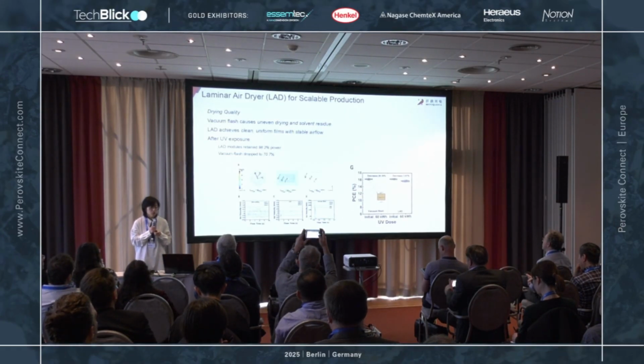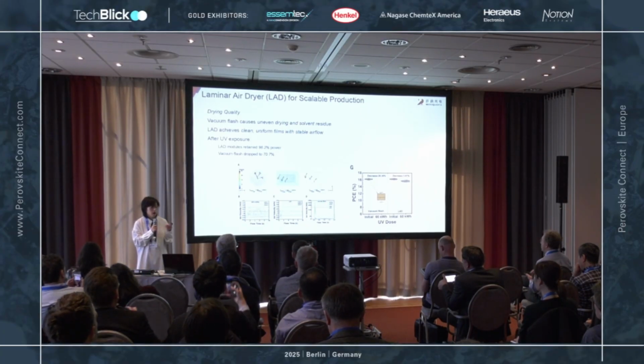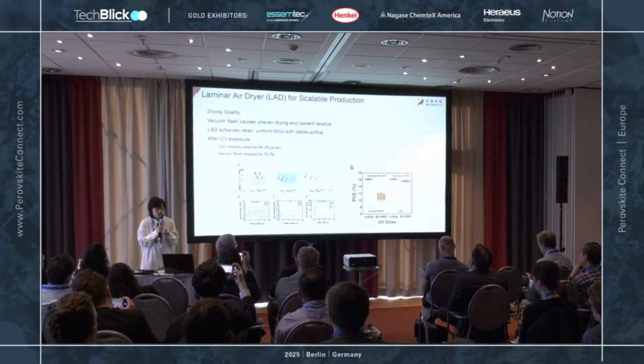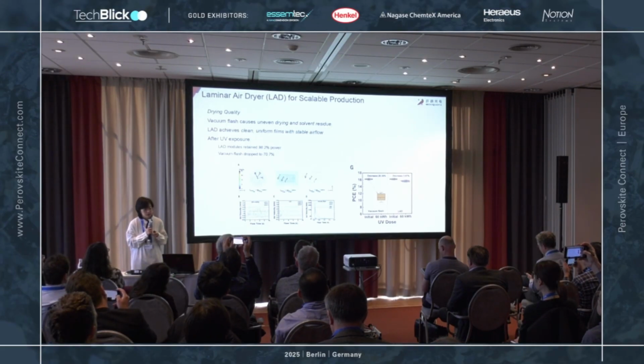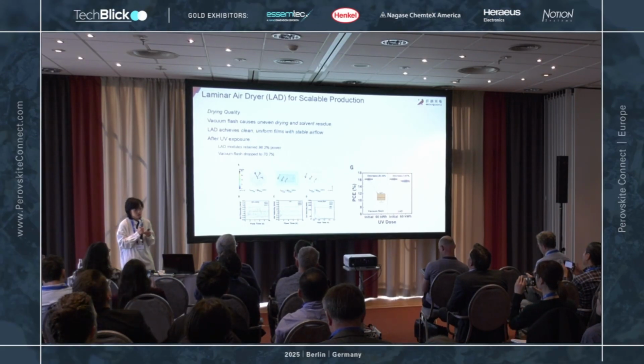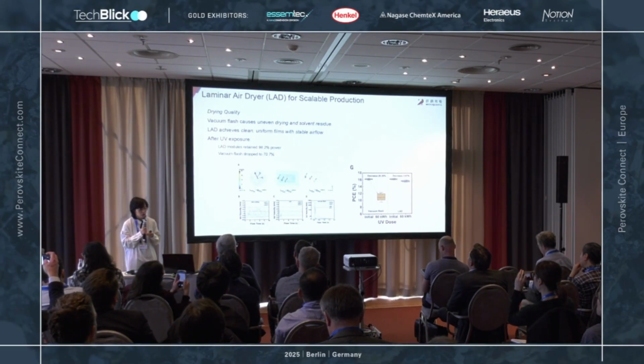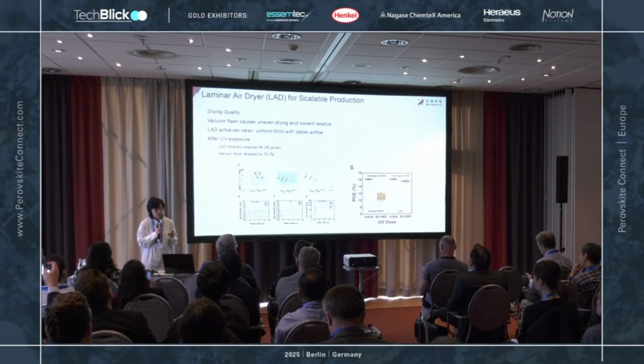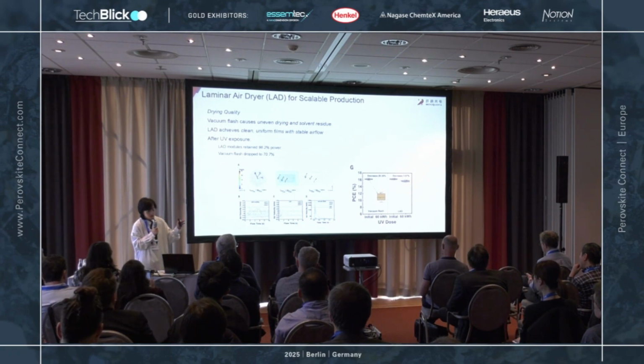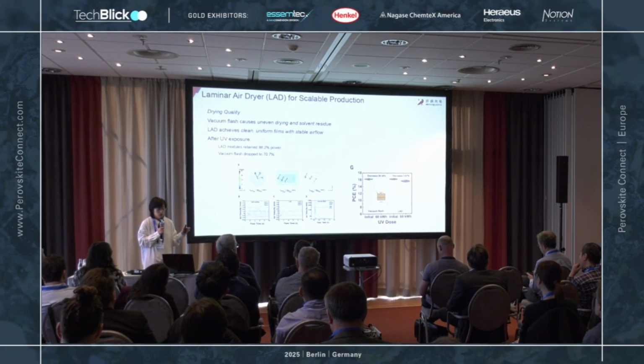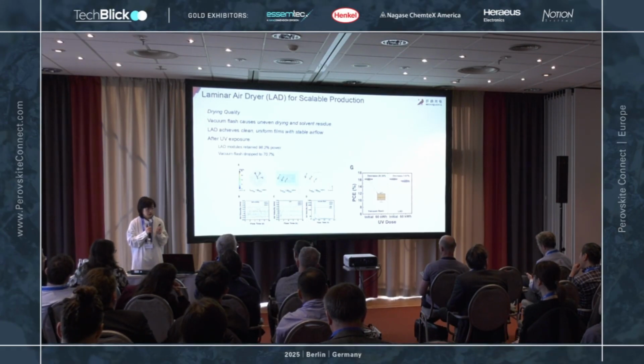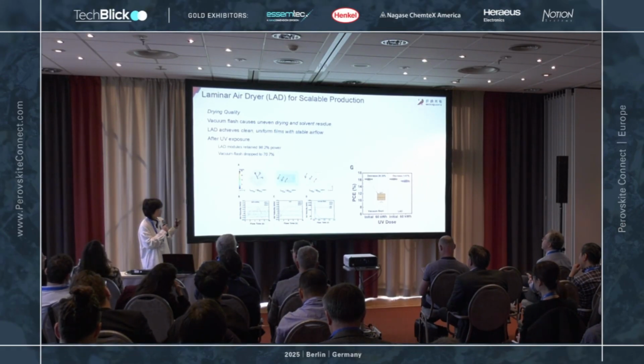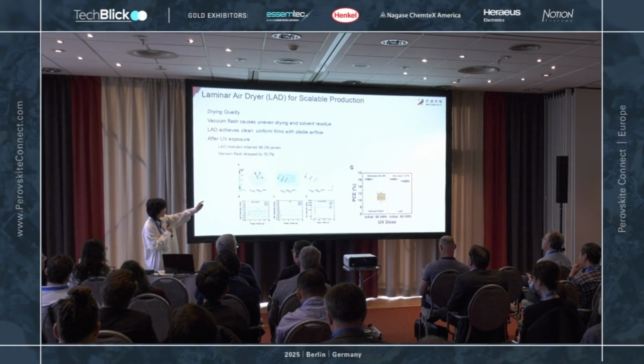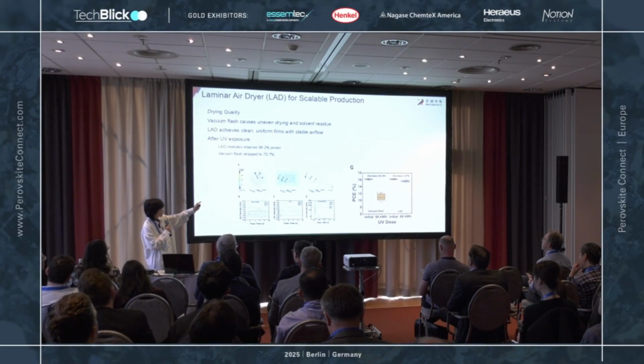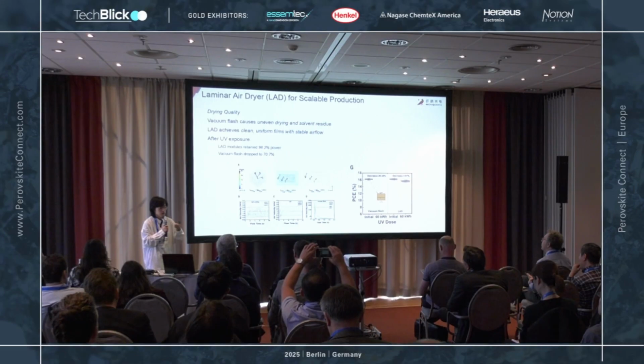One of the biggest breakthroughs for us is understanding the drying quality for perovskite solar. Compared to vacuum flash, which causes uneven drying and traps solvent in the crystallization process, our laminar dryer achieves clean, uniform films with stable airflow. Here on the right, after UV exposure, the laminar dryer still retains 98% power, while the vacuum flash drops to 70%. And on the left, the laminar dryer recreates the evenness of spin coating quality in this film.